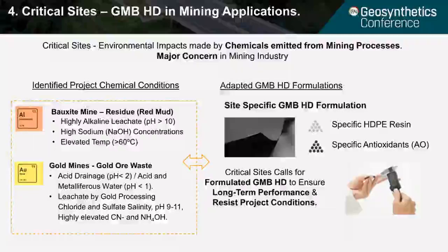Bauxite residue generates liquors with highly alkaline pH leachate, high sodium concentration, as well as elevated temperature of cooling water. And then gold mines generate acid liquors and can also generate another type of leachate by gold processing, with elevated chloride and sulfate salinity with moderate to strongly alkaline solutions. Traditional formulation will not resist these extreme conditions.